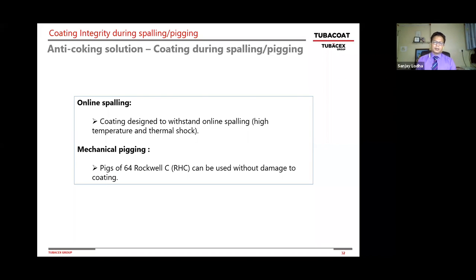Second part is mechanical pigging. Of course, our regular pigs, which are 82 or 84 Rockwell C, they are a bit too hard for something like this coating. So we have worked with the coating company and we have come up with the pig studs. Those are a little bit softer, 64 Rockwell C or 800 Vickers number, and they can do the mechanical pigging without any damage to the coating surface. And they can be available to any customer anywhere in the world. So we just modified that.